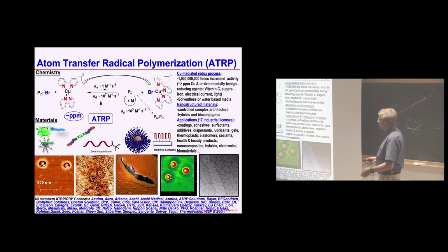So, going deeper into the atom transfer radical process. We have now developed catalysts which are 1 billion times more active than those originally used. They are extremely powerful, and therefore you can now work with parts per million of copper. We borrowed atom transfer radical polymerization from organic chemists, who use atom transfer radical addition. They worked at 10 mol% concentration versus monomer. So we worked at 1 mol%, then 0.1, and now we work really with parts per million. However, with such a small concentration of radicals, even if they exchange very fast to control polymerization, every act of termination will convert these activators to deactivators, and the reaction would stop.